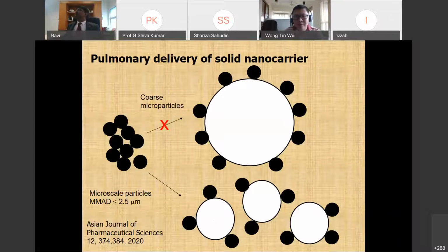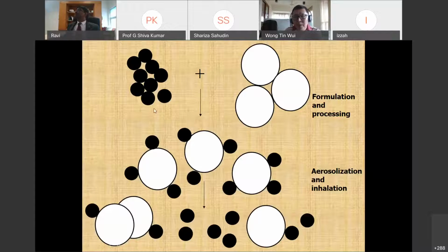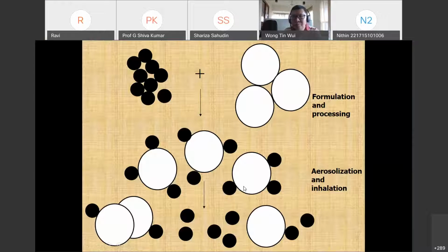As such, we hypothesize that we should deposit our nanoparticles on a micro scale particle, which is a few micron in size. Now let's take the hypothesis that we have derived. Nanoparticles alone, due to their small size and high specific surface area, tend to be aggregative. Likewise, micro scale particles, because they are only a few microns in size, are cohesive and aggregative. So by blending both in a specific weight ratio, you will have the nanoparticles adsorbed on the surfaces of the micro scale particles. Once the nanoparticle is adsorbed onto the surfaces of the micro scale particles, the aggregativeness of the nanoparticle is reduced. And the nanoparticles sitting on the surfaces of the micro scale particles can also act as a glidant, thus preventing the microparticles from aggregating with one another.